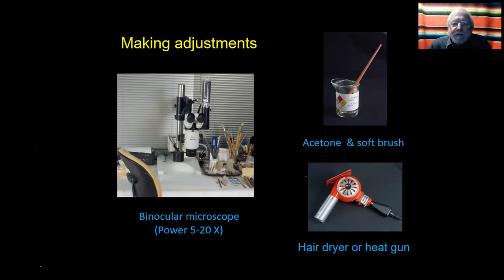Acetone is really necessary for cleanup, and you can almost immediately clean up one side of the glass, preferably the outside, because you're never going to see the inside on a vessel like that. But you can clean up at that point. And I usually do a little bit of cleanup just before looking at it under the microscope, and then I'll put it down and check it again later.